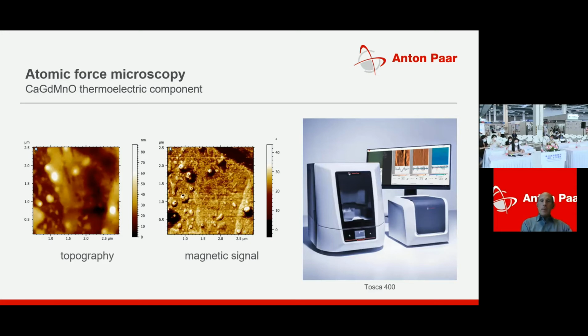The mapping of the topography, which you see on the left-hand side, using the conventional tapping mode of the atomic force microscope, shows some grooves and scratches, probably from the grinding and polishing process of the sample preparation, as well as some elevated and lowered positions that represent particles, pores, and holes in the material surface.